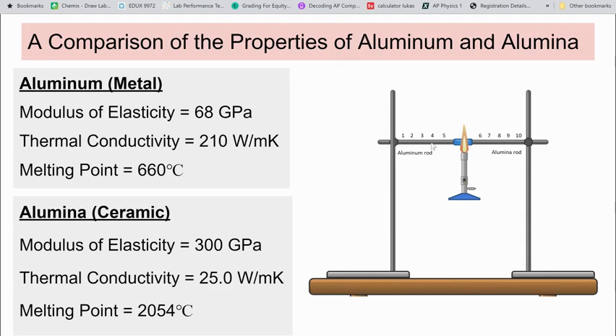And if you remember in our demo, all of the crayons, all the way back to position 1, fell off the aluminum rod because metals conduct heat very well. They're great conductors. Whereas the first crayon at position 6 on the alumina rod never fell off, even after crayon number 1 fell off. And that is because ceramics are very poor conductors of heat energy. They have a low thermal conductivity, which makes them a great insulating material used for things like refractories, furnaces, or engines.